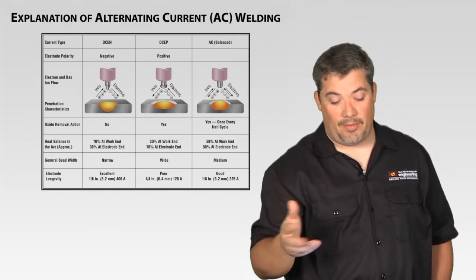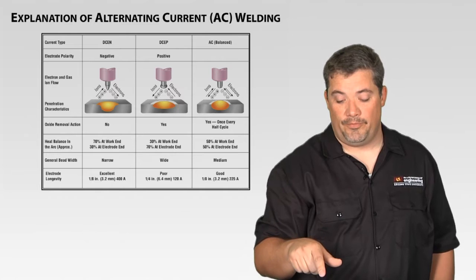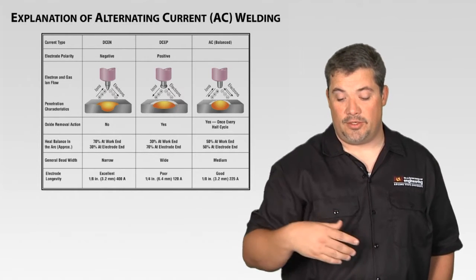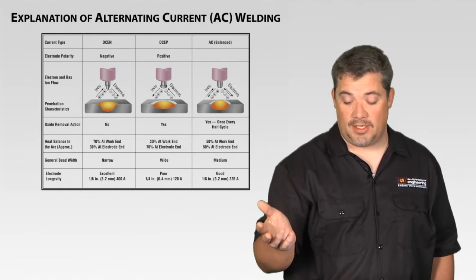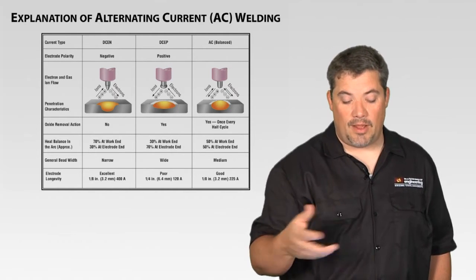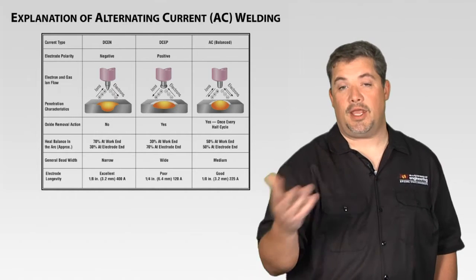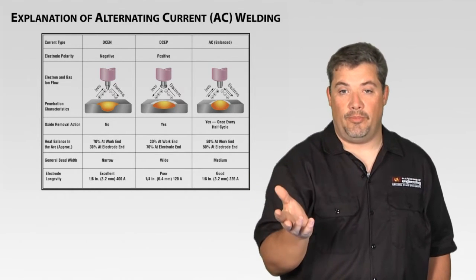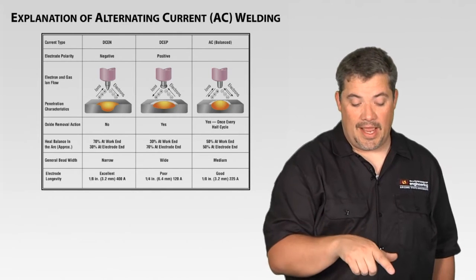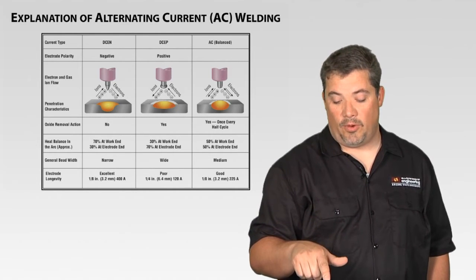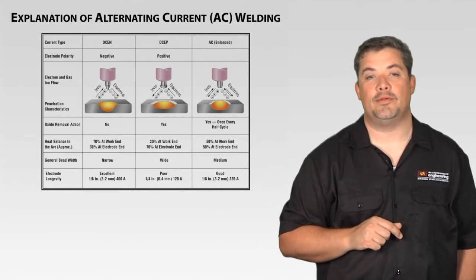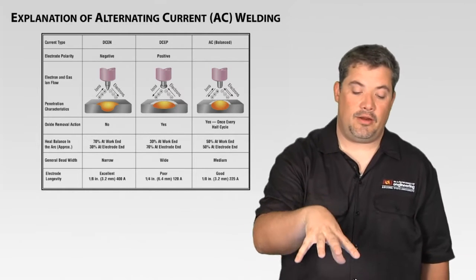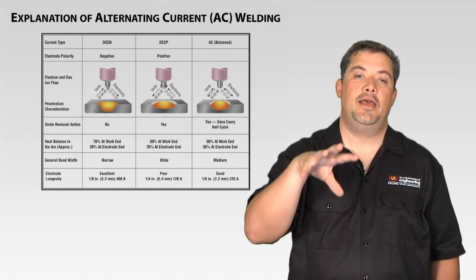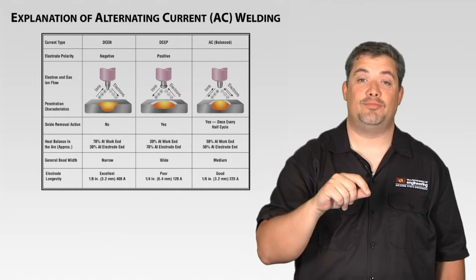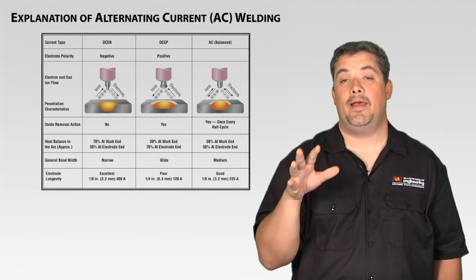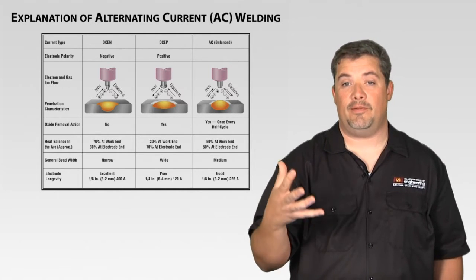So every half cycle I get my cleaning action, or my oxide removal. My heat distribution is balanced between the two, so it's 50-50. So 50% of the heat's on the tungsten, 50% is on the work, and my bead width is somewhere between the electrode negative and electrode positive arc. So the bead shape is somewhere between these two scenarios, and the electrode capacity is also somewhere between, where a 1/8 inch tungsten will carry about 225 amps. Understanding this chart right here is really the key to understanding advanced TIG welding. These advanced machines have some more controls on them for AC, and for me to understand the difference here.